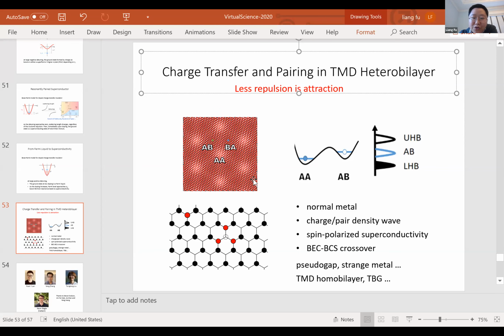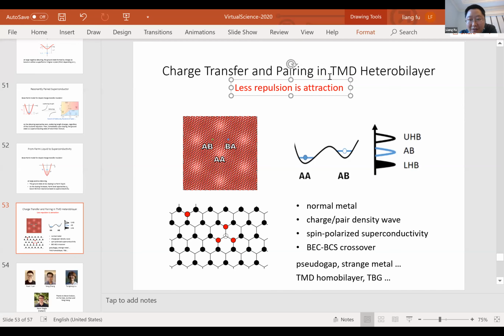Now, I've shown you that despite the two-body interaction being purely repulsive, a trimer can be formed, which is a charge 2e object, and this pairing is possible because the system can lower its electrostatic repulsion, in a very simple way. When the kinetic energy of the holes is small, these trimers can form insulating density wave states, a Wigner crystal of trimers.